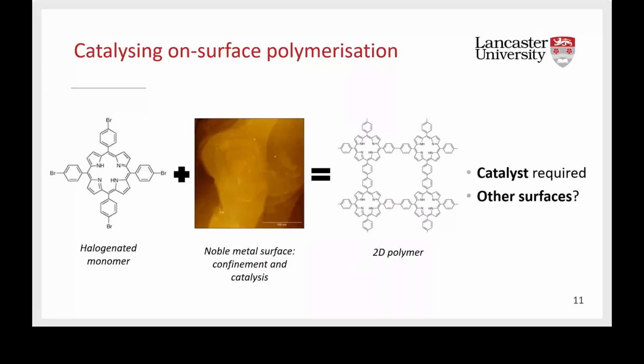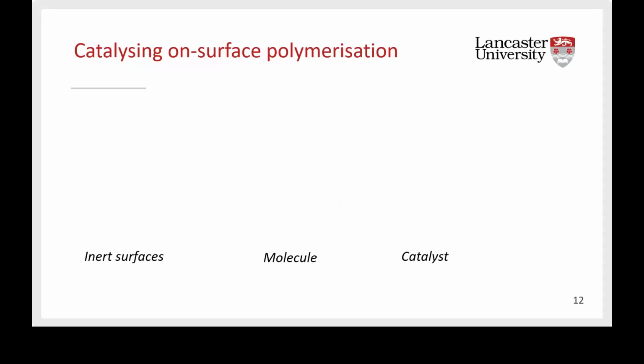Specifically, I'm using halogenated monomers. So monomers that have a carbon-halogen bond, such as carbon-bromine, carbon-iodine, or carbon-fluorine. And I deposit them on noble metal surfaces that have two purposes. First, the surface confines the monomer into two dimensions, and second, it catalyzes the carbon-halogen bond cleavage, so that the monomers become radical and can then polymerize into polymers. However, as you can see, the noble metal surface has two purposes: it confines the monomer and catalyzes the polymerization. And in my research, I'm trying to decouple this process, so that we have three main characters.